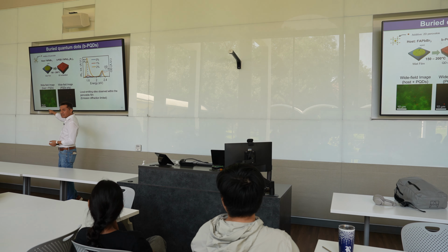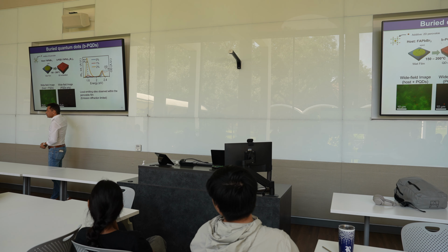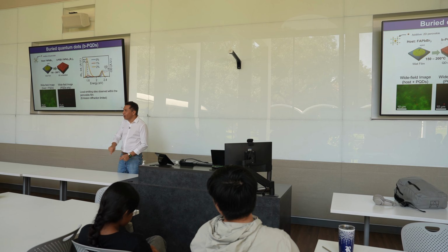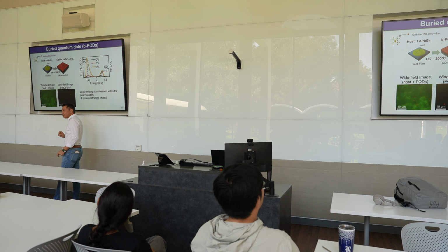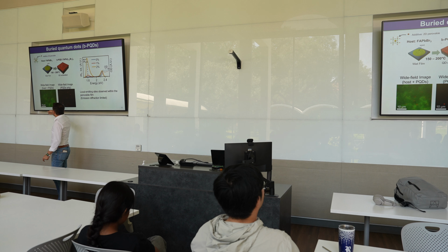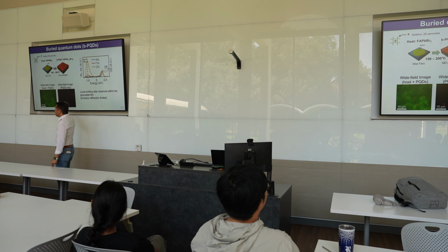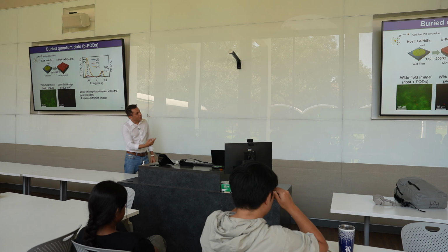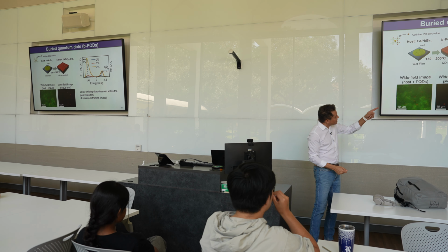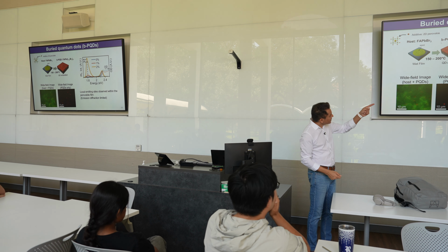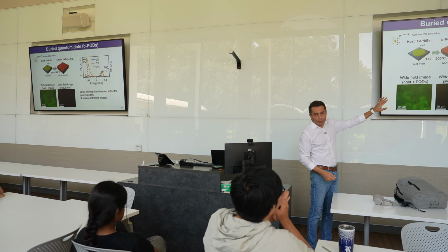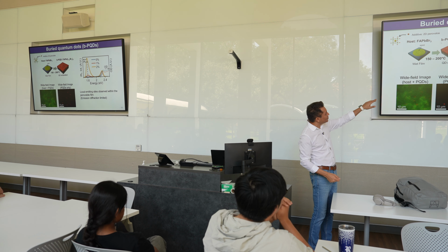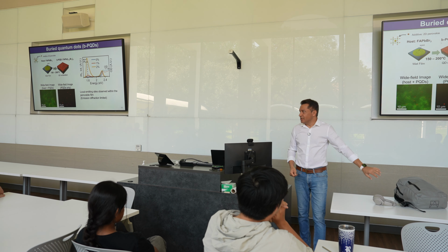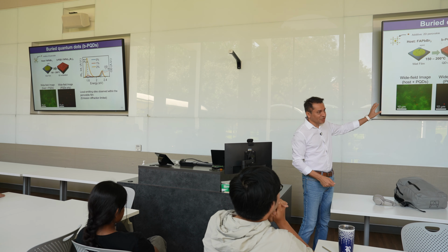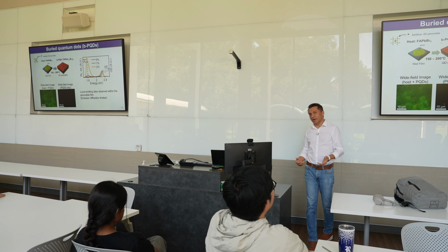But when I look at the photoluminescence, this is what they look like. I see the green, that's the background, that's the host matrix. It's a large band gap. So you see this green color, but then I see these dots. These red dots are these single photon emitters at room temperature. This is what I've grown. If I put a green filter on it, then I get essentially these dots which are emitting. At room temperature, this is photoluminescence as a function of excitation energy. You see the host matrix, that's 2.2 electron volts. But then you see this emission which comes from, with just about 2% of doping or additive, you start to see this emission around 1.6-ish. That's coming from these iodide quantum dots that have now grown.